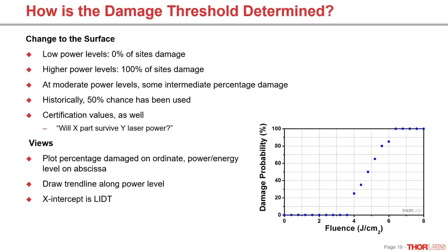As far as how damage threshold is determined, here's a very brief overview of the testing process. Basically, at lower power levels, if I direct a 2 milliwatt helium neon laser onto my surface, I'm not going to see any damage, no matter how long I do it for, on most optics. And at relatively high power levels, I am going to see damage everywhere I hit with the laser. If you do something like that, you can start to get data points like this and like this.